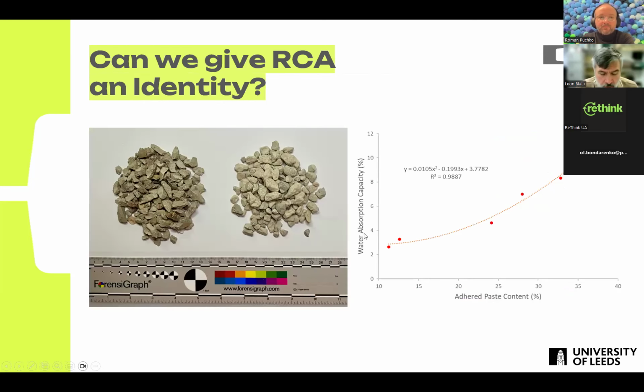So can we give recycled concrete more of an identity? What can we find out? What can we learn about recycled aggregates, so that by understanding these properties, it allows us to make better use of the materials? This photo here is taken from the laboratory concrete. This was crushed aggregate. It's very angular. It contains lots of adhered mortar. And then we processed it. We basically tumbled it in a mixer to remove this adhered mortar. And this is what we were left with at the end.